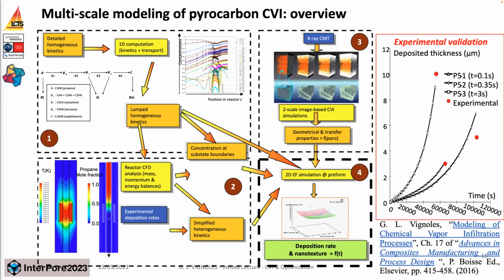So this slide summarizes many years of work in which in my lab we developed a multi-physics and multi-scale approach to chemical vapor infiltration. In the first block, we worked on the homogeneous kinetics of hydrocarbon decomposition, so that we could identify what are the exact species that are going to react with the surface and leave this carbon deposit. In the second block, we have also performed CFD analysis of the furnace, the reactor with the porous medium inside, without any detail on the porous medium. But if you do so with a flat medium, then you may have access to the heterogeneous kinetic rates. Now, if you merge that with the homogeneous, you get a full chemistry package.